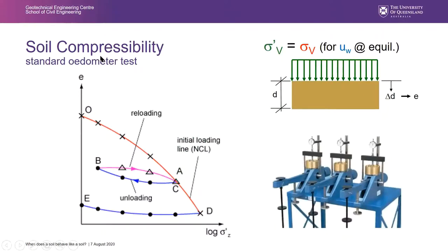So that is the standard oedometer test. We have a relatively thin sample, 2 centimeters or so. We apply a stress on the surface, and at equilibrium, when excess pore water pressures have been released, the applied stress corresponds to the effective stress, and any deformation, if we know the initial void ratio, changes the void ratio. So these are then the points of these equilibriums, starting from the initial void ratio.